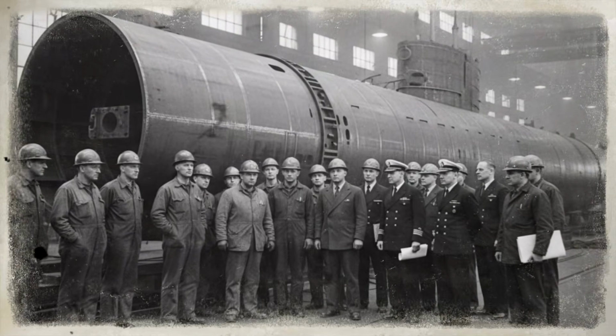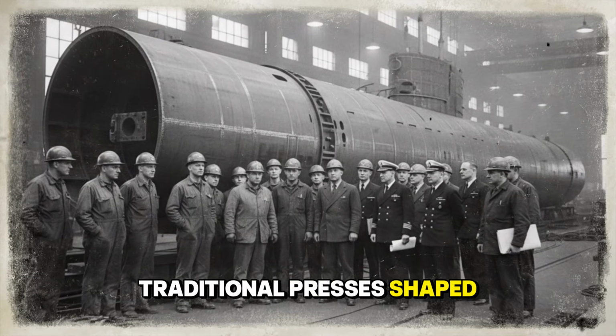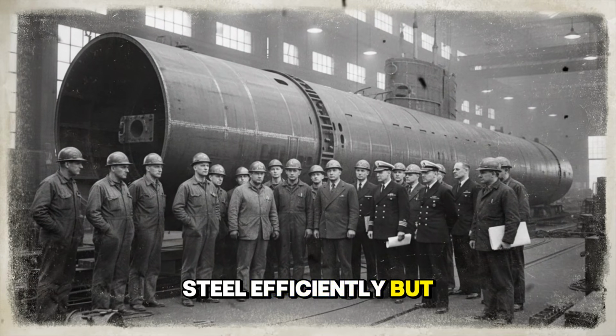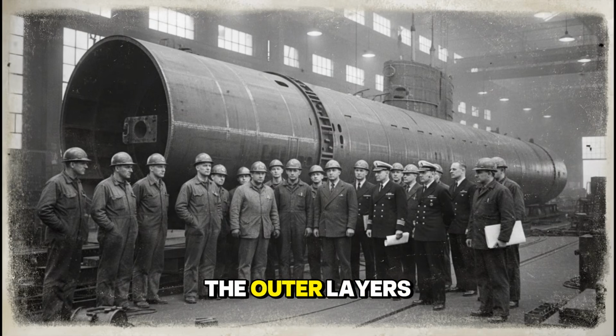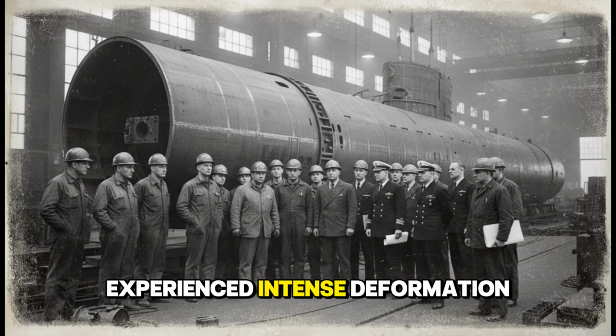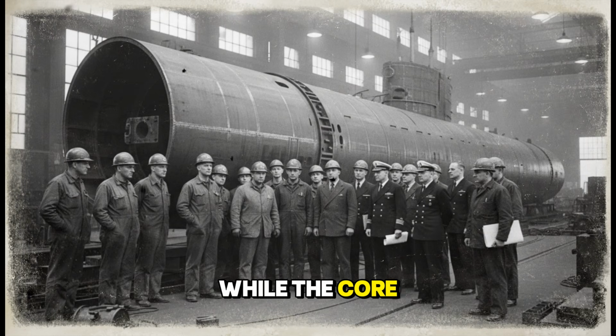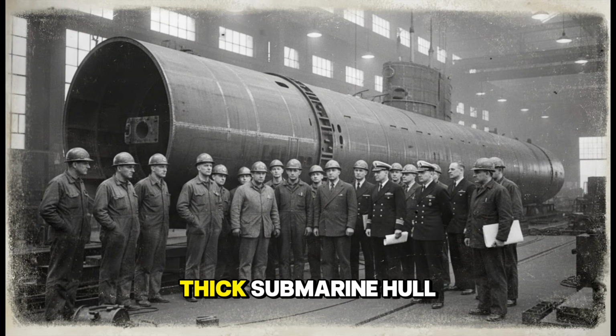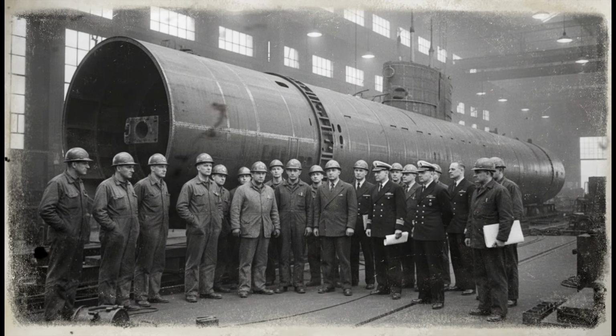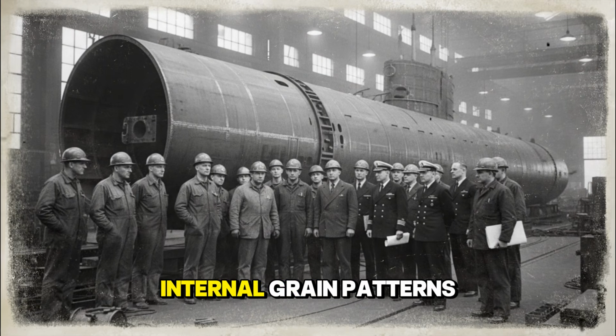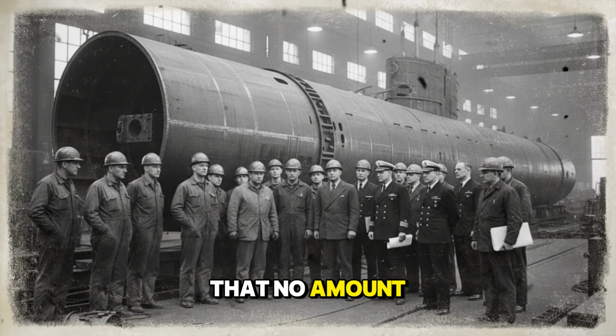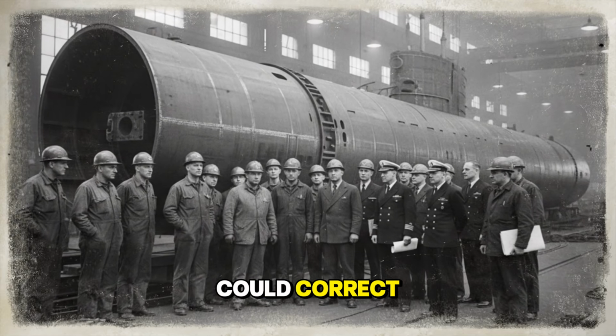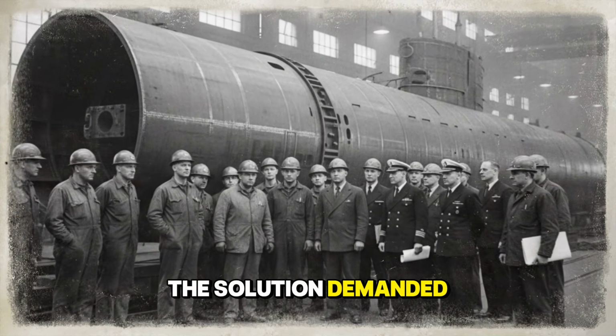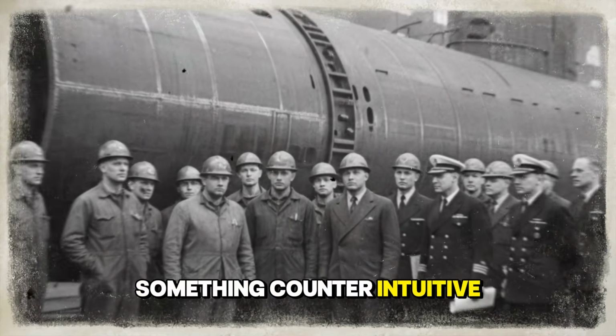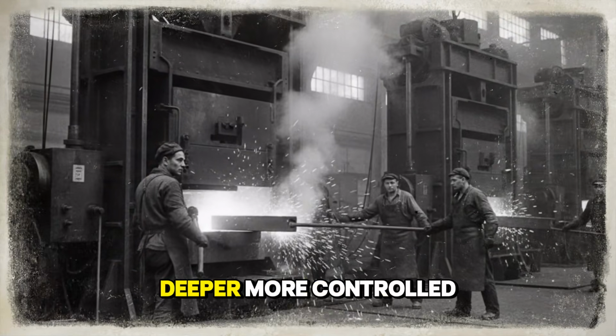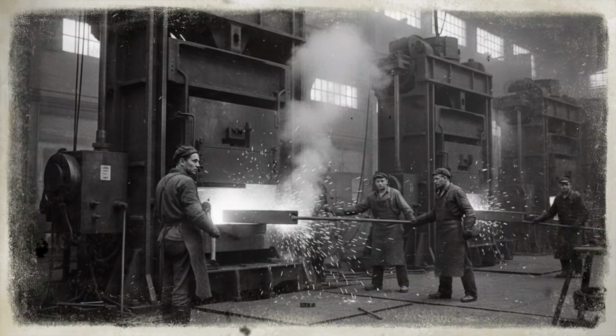Traditional presses shaped steel efficiently, but unevenly. The outer layers experienced intense deformation, while the core lagged behind. In thick submarine hull sections, this imbalance produced internal grain patterns that no amount of surface finishing could correct. The solution demanded something counterintuitive, slower, deeper, more controlled force.